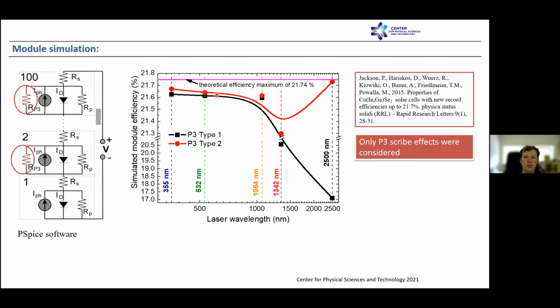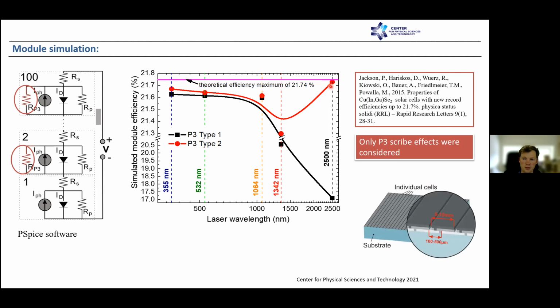But we see that for UV or green or even 1064 nanometer wavelength, the efficiency losses are quite low. But if we switch to deeper infrared, 1342 nanometer, we see that efficiency losses become higher. And if we even switch to nanosecond laser processing, we see that P3 type 1 gives a really low result, so efficiency drops significantly. However, if we use the P3 type 2 process, we see that efficiency is really high, comparable to the theoretical efficiency of a single cell. We have 1 more minute left.